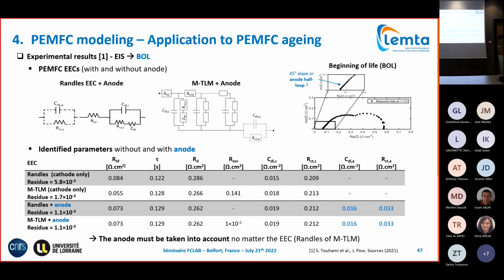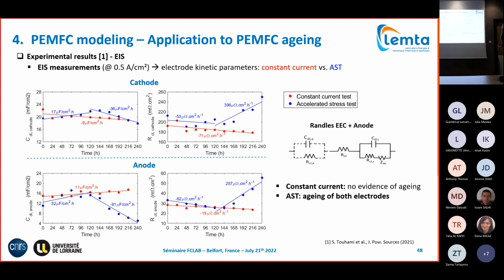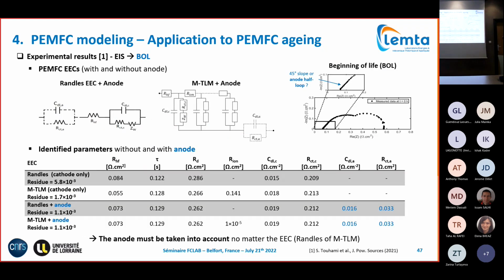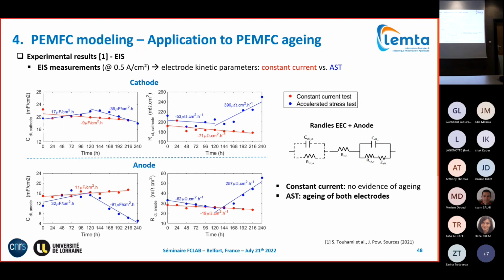We can identify the double layer capacitance and charge transfer resistance at the cathode and the anode, which gives us information about how the reaction kinetics evolve, whether they increase or decrease. Here this tells us we have slower reaction dynamics, slower performance of the reaction kinetics with time. It seems that the electrodes are less performant to ensure the electrochemical reactions. We will also identify the diffusion parameters, but as we are still not really clear what the physical meaning is, I'll skip this at the moment.